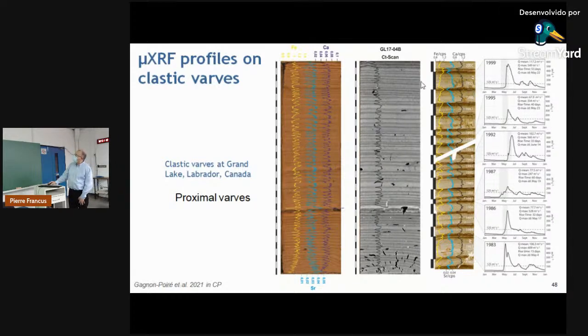And we can measure these profiles year after year, and what is interesting is that in this setting we have an instrumental record of the river discharge, and here on the right panels are different measured hydrograms. You can see that, for instance, 1983 has a lot of water, and the 1983 varve is very thick. So the theoretical model is working. To the opposite, if you go to 1995, it is this varve here. It's a very thin one, and you see that a lot less water entered into the system.